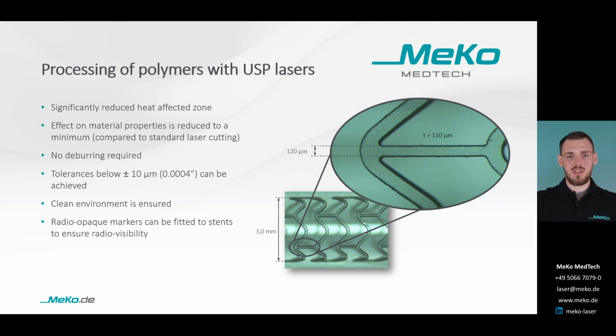Due to the USP laser technique, there is no further process step like deburring or cleaning required. The process itself takes place in a clean environment to minimize any contaminations. The cutting edge quality and strut width tolerances are the most important aspects to assess the laser cutting quality. And the cutting edge here, as shown, is very clean, and this small black looking edge is caused by the refraction of the light at the edge. The component has almost not seen any heat influence, especially with polymers. This would be directly reflected by a strongly melted or even burned cutting edge. The accuracy here is better than plus minus 10 microns. You can see the strut is very consistent, and this is also significantly influenced by the quality of the tubing.